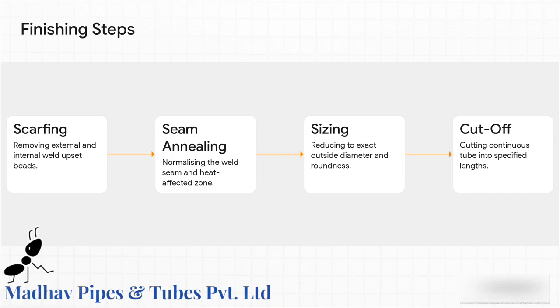Next is seam annealing. The extreme heat of welding can actually cause hardness peaks, which makes the steel brittle. So an induction coil reheats just the seam area to about 920 to 960 degrees Celsius and lets it air cool. This normalizes the structure and eliminates residual stress. Third, the pipe travels through a multi-stand sizing mill. This corrects the outside diameter to an exact tolerance of plus or minus 0.5% and perfectly straightens the tube.